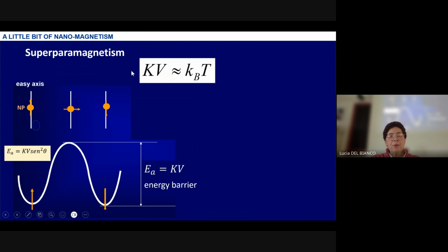But if the volume of your nanoparticle is really small, it can happen that the height of the energy barrier, KV, is comparable to the thermal energy of your particle, namely temperature times the Boltzmann constant. And therefore, in this condition, the moment of the nanoparticle is able to overcome the energy barrier, flipping back and forth without the need of an external field. And in this case, you have a superparamagnetic nanoparticle. Namely, the moment has the possibility to overcome the energy barrier even without an external magnetic field. And so in any instant, the moment can point in any direction, okay?